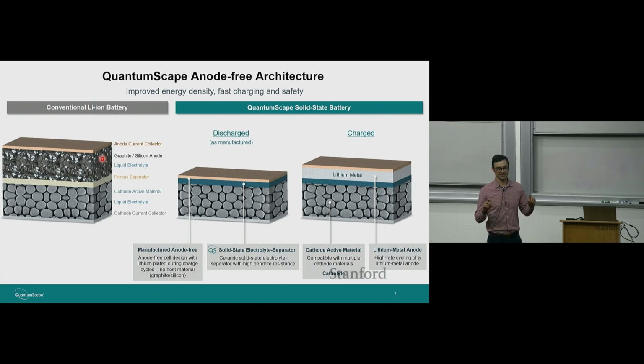The ceramic is a solid state electrolyte. It allows lithium to pass, but it's made in a way to try and prevent dendrites. It's also made to try and prevent the other main degradation mode of lithium metal in the liquid system, which is what's called low coulombic efficiency. So lithium metal is one of the most reactive materials you'll ever encounter, and it reacts with virtually every liquid electrolyte.